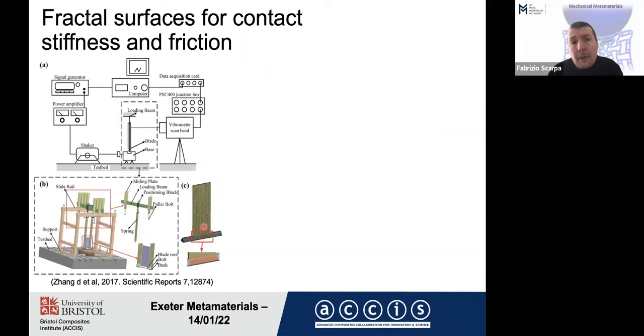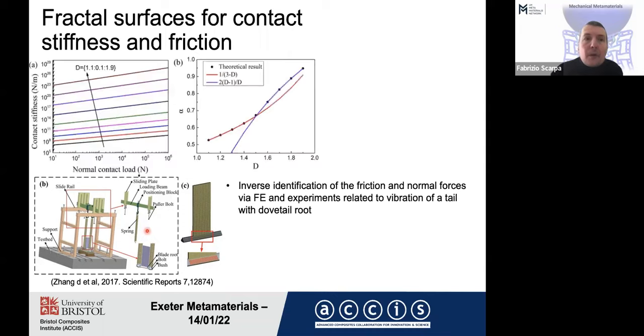And we also built this rig to measure the contact stiffness during dynamic loading for dovetail blades at the base. We used laser vibrometers and inverse identification using also finite elements, in which we applied these contact surface models. And quite interesting, in terms of contact stiffness, if you want to increase the contact stiffness, you want to increase the fractal order of the asperities. And you can clearly see that, especially in this relation with the normal contact load. With the contact asperity, you also increase the equivalent friction coefficient. And friction actually is an excellent way to dissipate energy, especially at low frequencies.